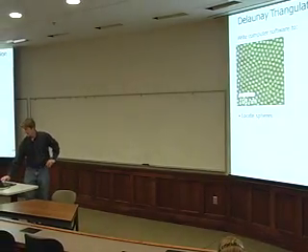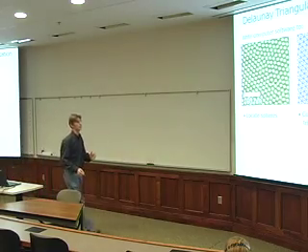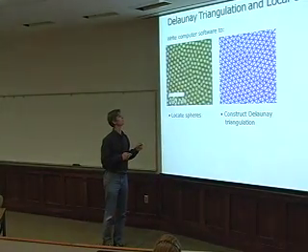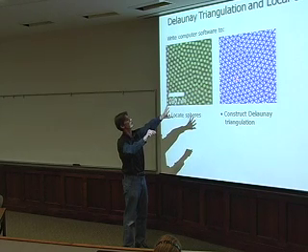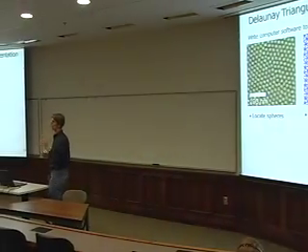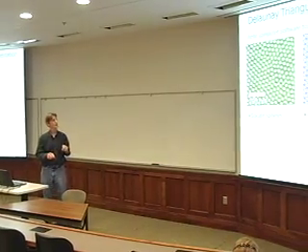I mentioned that these are in fact lined up in rows in a hexagonal lattice, and sure enough, there's an analysis we can do to pretty much figure out mathematically what the nearest neighbor is for each one of these. And we see that this is the same data represented here on the right, where I haven't shown the initial picture, but I have shown simply the connections from each sphere to its local neighbors. And you see that each one sits in the middle of a hexagonal cell. And here again, it's very easy to see from the lines that these are lined up in rows.